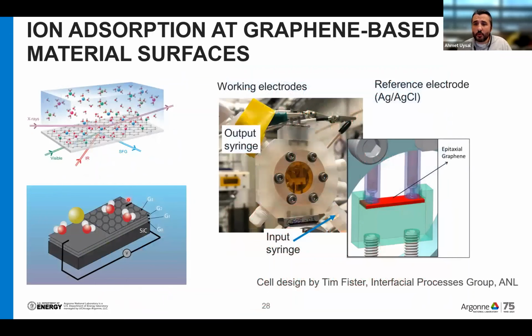One experiment I'm going to mention is trivalent ion adsorption on electrified graphene. What we do is we have epitaxial graphene on silicon carbide, and we apply a potential. We have a trivalent yttrium solution in our sample cell. Here is the real sample cell that we use at sector 33, and we look at the surface and how ions are adsorbing and how water is behaving at that interface.